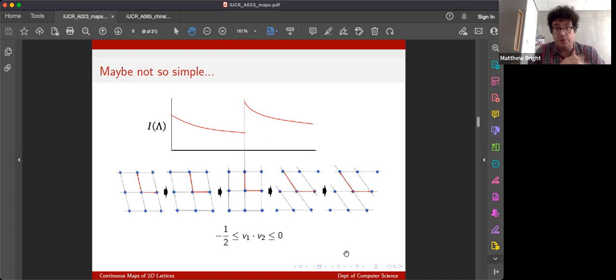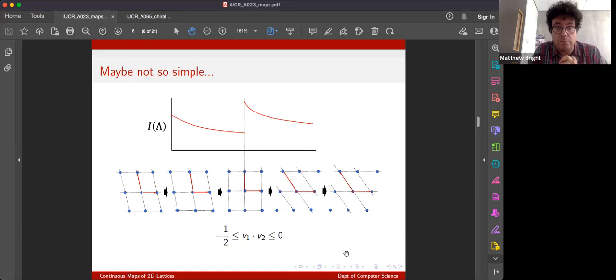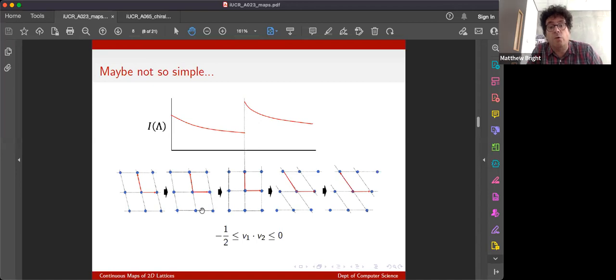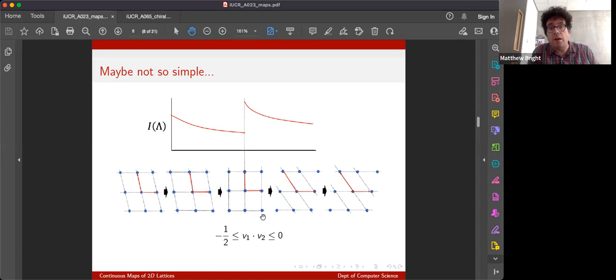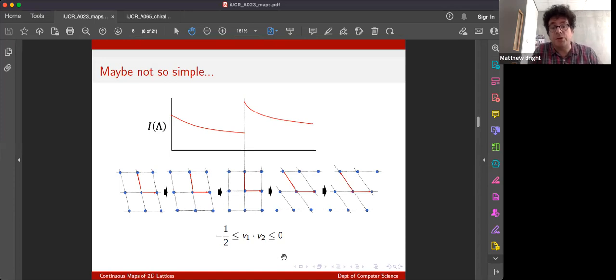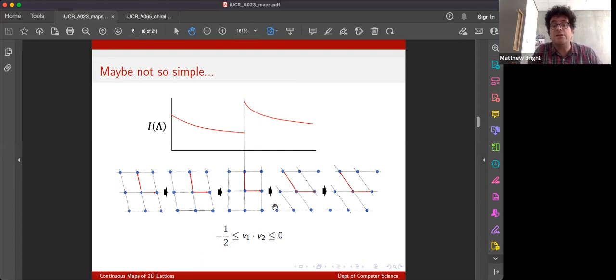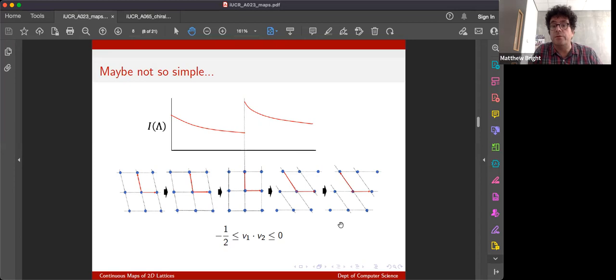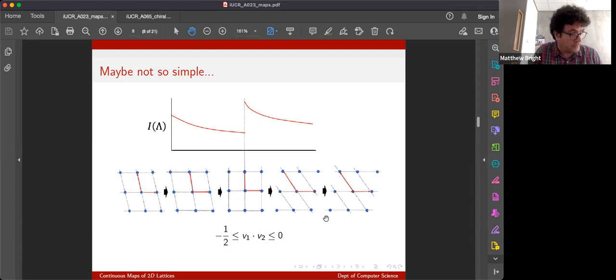But, and in fact you can prove this for any reduction, this schematic illustrates why that's a problem, why using any reduction is a problem. As I gradually change, as I gradually deform this lattice here, and as it passes through a higher symmetry position, any reduction I choose, in this case again I've chosen the reduction to enforce an obtuse angle basis, will suddenly change discontinuously, and therefore its parameters will change discontinuously, because it's going to choose a different pair of basis vectors.